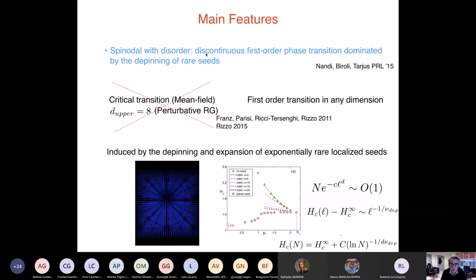Now, the upper critical dimension for the spinodal transition is 6. You can do a mean field theory. If you put disorder on top of it, again you can do mean field theory. As you know, for the random field Ising model, if you do perturbative RG, there should be dimensional reduction, and so the upper critical dimension should be 8. So you would expect that the spinodal is critical, and the exponents change below the upper critical dimension, which is 8. This is what you find naively using mean field theory and perturbative RG. But this actually is not correct.